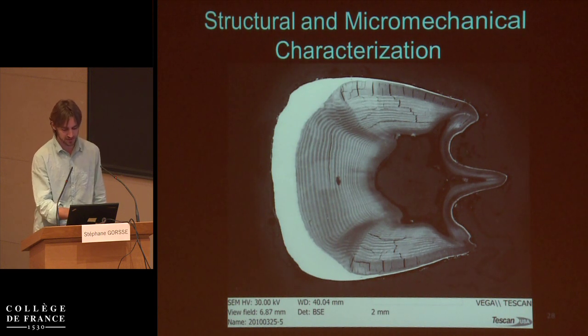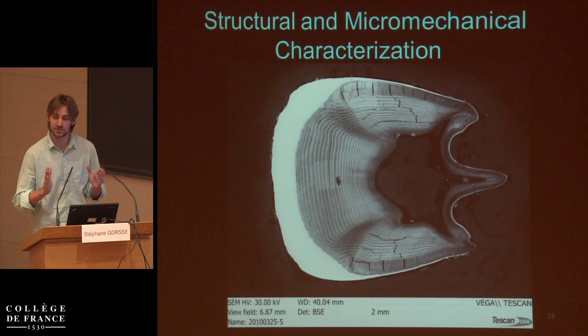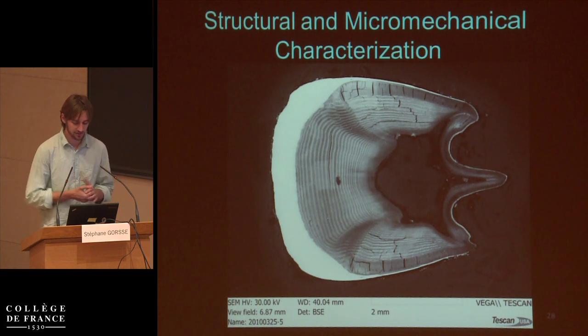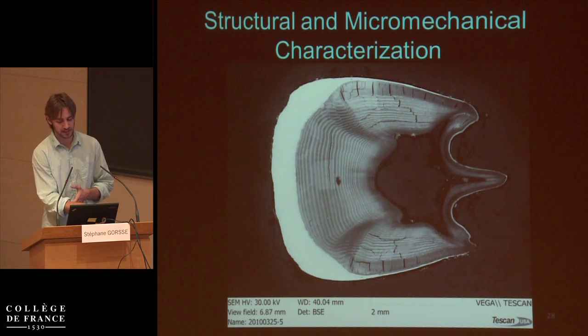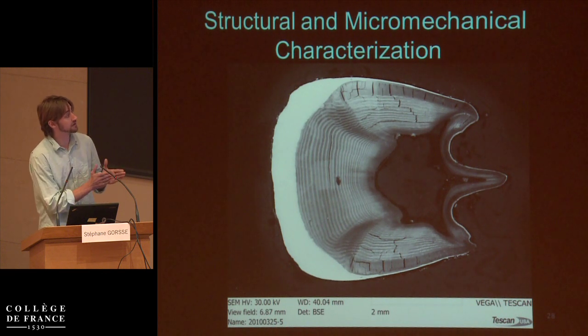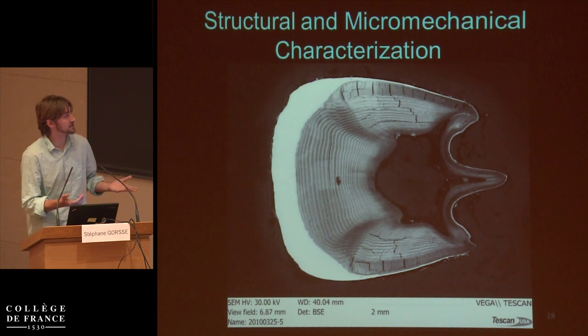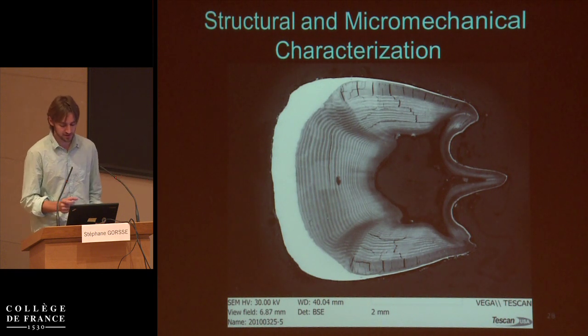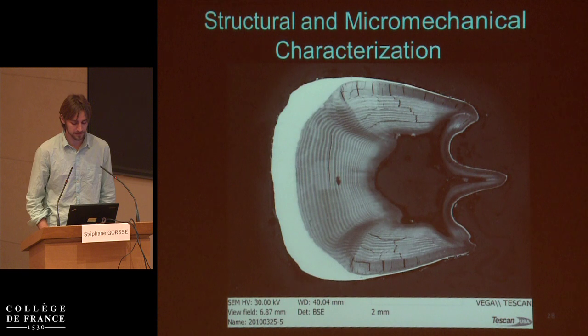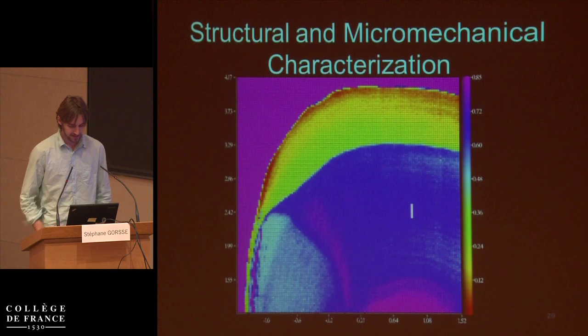The pitch, which is the amount of distance you need to travel to make a 180-degree rotation or 360-degree rotation. But what you're seeing here is these lines. So every line is a 180-degree rotation. The pitch would be defined as 360 degrees. That pitch is so much larger than what you typically find. Normally, 10 microns is about the upper limit. There's certainly things higher than that, but this can get up as large as 300 microns. And it's this very graded architecture, which we'll get back to.